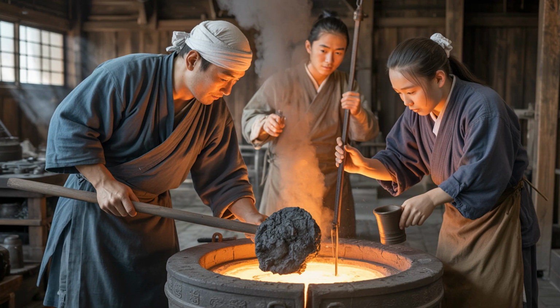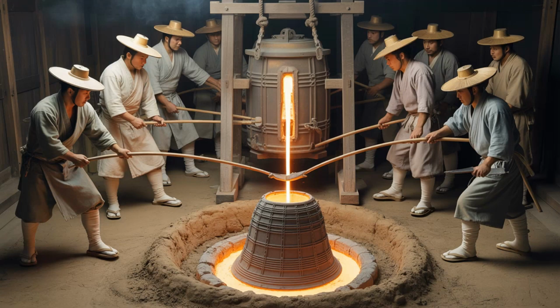Testing the bronze was an art that bordered on insanity. Some smelters would dip iron rods into the molten metal and examine how the bronze behaved as it cooled on the rod. Others would pour small test samples into clay cups and crack them open to examine the internal structure of the cooled metal. The most experienced could even tell if the alloy was right by the sound it made when they stirred it with their tools. Different bronze compositions created different sounds when agitated, and a master's ear could detect variations that would escape everyone else.